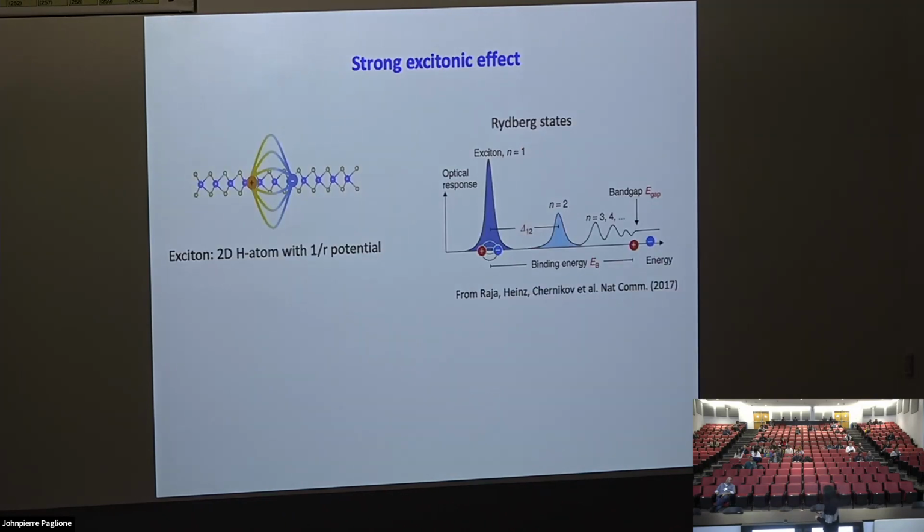That something else is the electron hole Coulomb interaction. We call it excitonic effect. Let's imagine you have a single sheet of a semiconductor. Optically, you excite positive and negative charge. Because the electrical field lines are so much outside of this material, the screening is very weak.